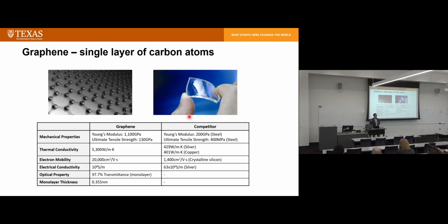Because when we compare materials, for comparators, that's bulk property. For graphene, people are talking about single crystal graphene. So we're not so interested in other properties. For us, electrical conductivity of graphene, although it's not that high, is still electroconductive. And optical property, 97.7 percent transparent. So we're using these two properties of graphene material. In addition, it's very thin, so there are a lot of applications. We don't have to focus on single crystal graphene. We want to focus on large area graphene, because if we can make this material electrically conductive and optically transparent, you can use it for a lot of applications.